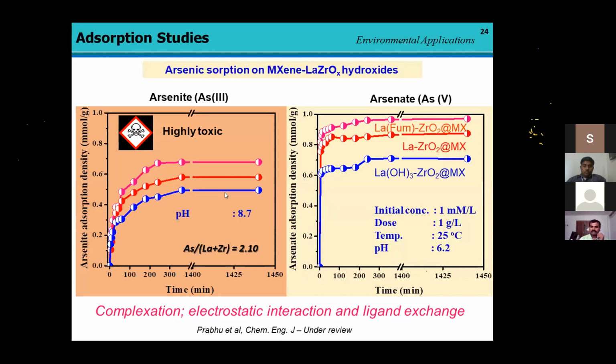2 arsenic ions. That means each lanthanum ion can adsorb 1 arsenic, as can zirconium, and both lanthanum, oxygen, and zirconia can form a bond, lanthanum-oxygen-zirconia, which can adsorb arsenic by a bidentate complex rather than a monodentate complex. This is the most valuable point for the adsorption studies. Then the mechanism was complexation, electrostatic interaction, and ligand exchange.